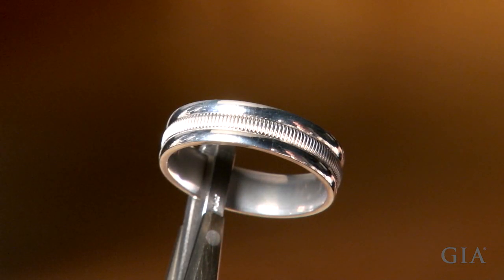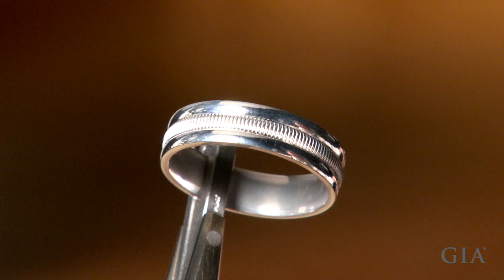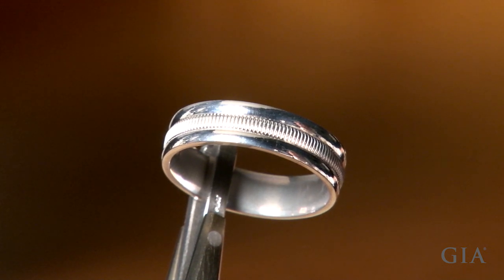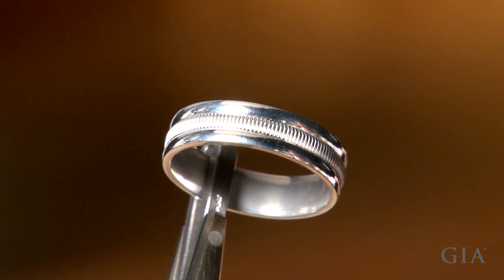The inside of the shank has turned a light frosty white color which is common after heating a piece made of platinum ruthenium alloy. It is also a good indication that annealing temperatures were reached in the process.